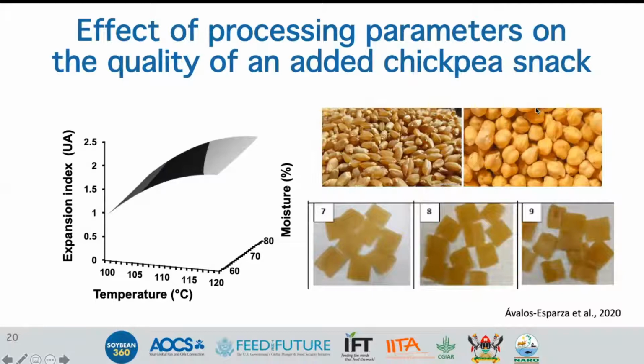We observe that the higher the temperature and moisture, the higher the expansion rate. This is because proteins influence expansion due to their ability to affect the distribution of water in the matrix and its macromolecular and conformational structure, which affects the extensional properties of extruded melts. Starch and protein fractions compete for available water in the matrix. This alters the viscoelastic properties by delaying the gelatinization of starch, which generates less moisture and affects the expansion rate.